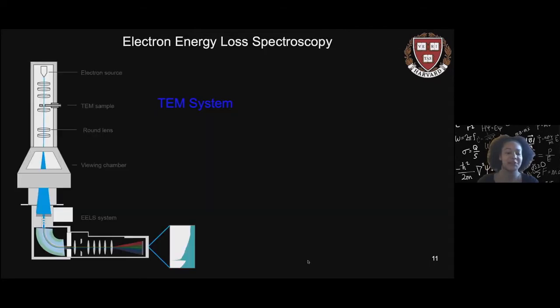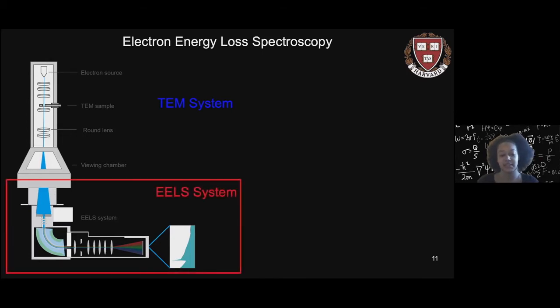So here I presented an image of the TEM EELS system. As the graphic showed on previous slides, here we have the TEM system where we fire an electron beam through our sample, which is then focused and imprinted based on the atomic resolution of our sample itself, and we're able to get our TEM image. The second half of the system is the EELS system. And the way that the EELS system works is similarly by firing an electron beam through our sample, but rather than being interested in the image the electron beam produces, we're interested in the amount of energy that the electron loses.